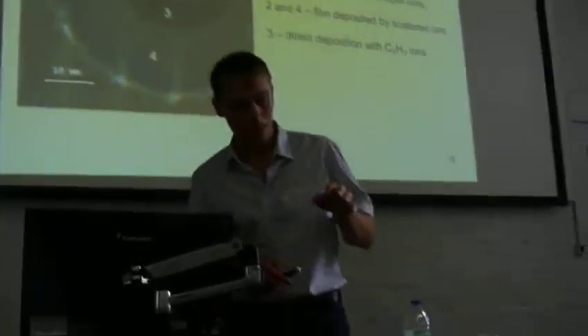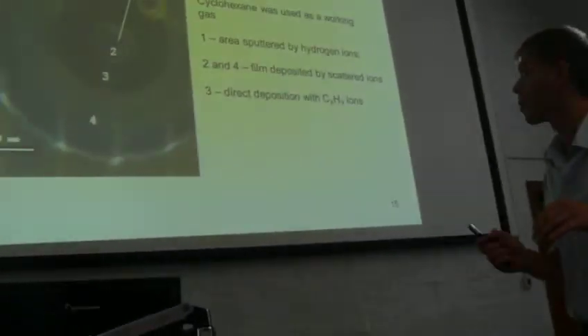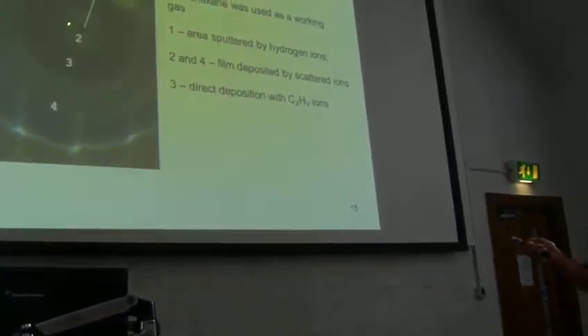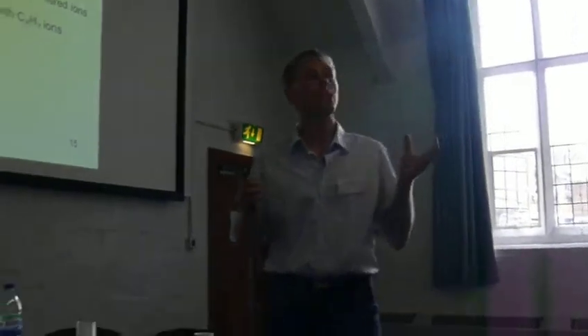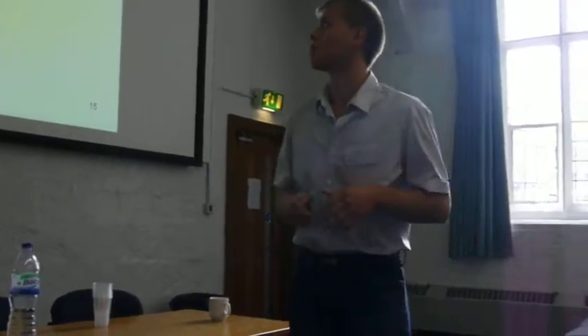Now I will try to answer your question. This picture shows us that hydrogen is focused in this spot. If there were some impurities, 5% or smaller or bigger, they will be separated, and they will be on this circle, this circle, this circle. The more mass, the larger the diameter of the circle. So if you have some percentage of impurities, it will be on the edge of your sample, so the central part can be irradiated with a pure ion beam, and this size of the spot allows all the surface diagnostics or analysis to view the results of irradiation. So you use spectroscopy to measure this, right?